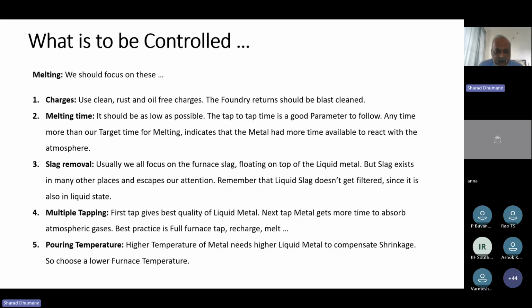If you are not able to do that, try to minimize your taps by taking actions in other places, where you can probably use a higher capacity ladle, or do some multi-cavity moulding, so that you are able to reduce your taps, and that gives you the best benefit on your melt quality. So when you have melted the best quality of charge, and taken sufficient care to melt it in minimum time, and then you do multiple tapping, naturally your quality deteriorates and your risk of shrinkage defect increases.